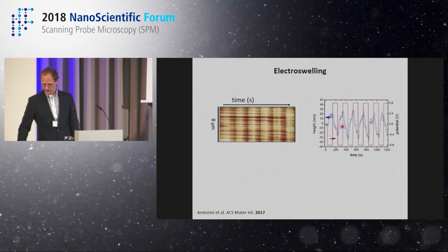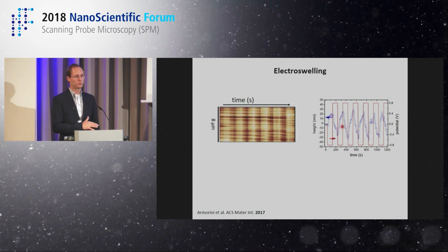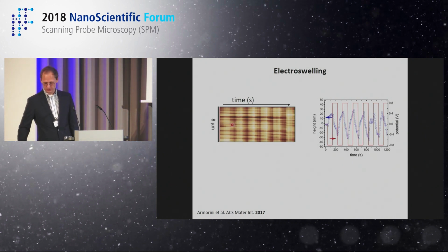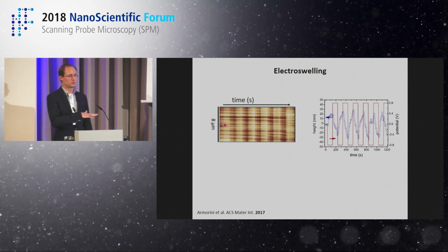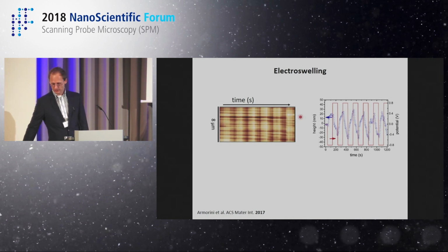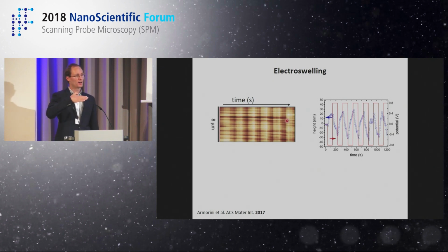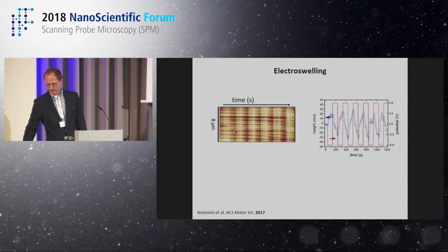However, also here, oxidation state was not the one that was impacting on the mechanical properties. The interesting thing that you then can start to observe is just when you do the live experiment. While you're measuring AFM, you start to change the oxidation state and then see what's happening. And this is an image that I take where I have just a line scan without moving forward or backward in the slow scan direction, and just collecting in time always the same line while I vary the potential applied to my polymer. And then I can see these kind of images.